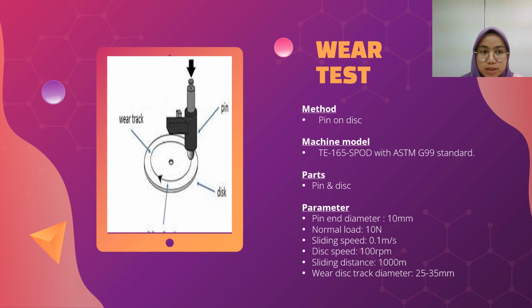The machine model used for this test is Magnum TE165 SPOD with ASTM G99 standard. This research was conducted to determine wear volume loss for pin and disc. The testing involved two different parts that were sliding over each other, a pin and a disc. The coated sample was fabricated into a pin with a cylindrical shape and slid against the disc. Both specimens were tested using the same parameters: pin diameter 10 mm, normal load 10 N, sliding speed 0.1 meter per second, disc speed 100 rpm, sliding distance 1000 meter, and wear track diameter 25 until 35 mm.